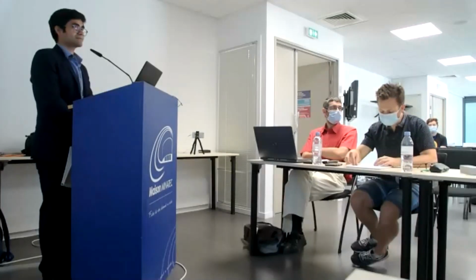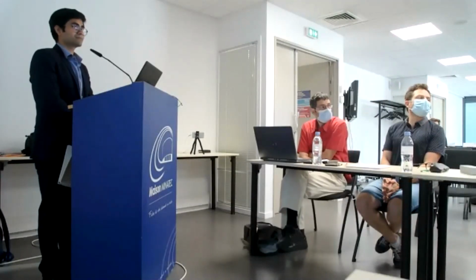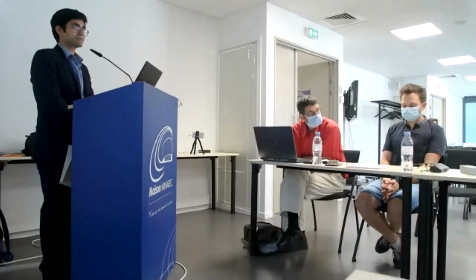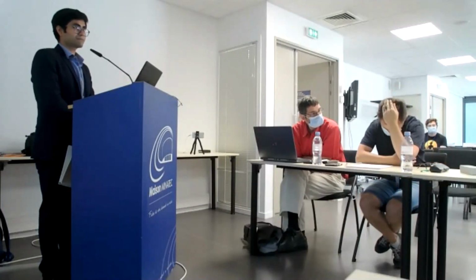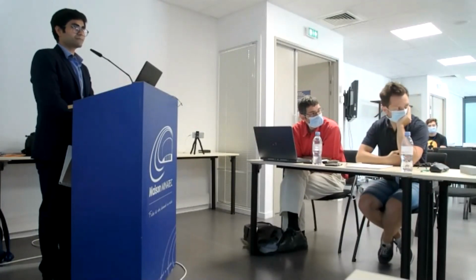Yes. I really appreciated also the fact that you showed that some liquid film can survive down to 400 degrees. It's the order of magnitude, okay, but it's really below the classic solidus temperature, and those are really the detrimental aspect of the whole structure, solid and liquids, because the liquid cannot sustain any tensile stresses and deformation. Yeah, I really appreciated this.